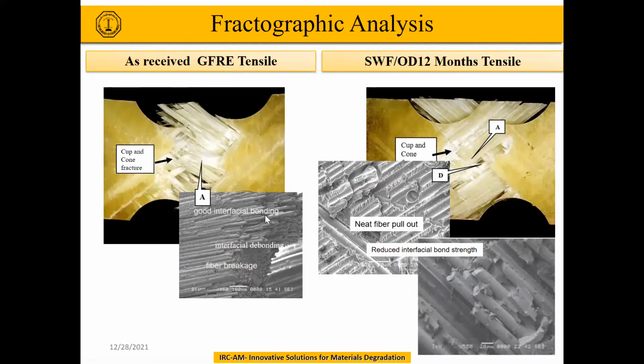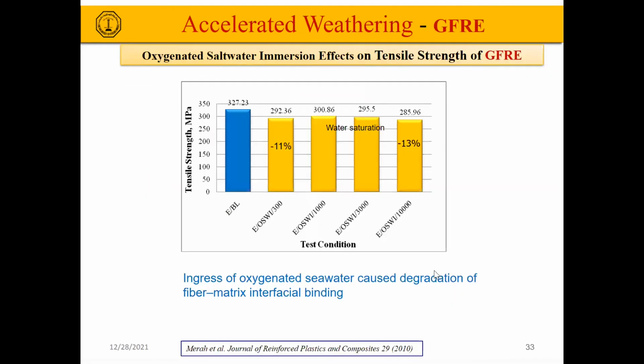We see that there is good interfacial bonding. There is interfacial debonding, and there is fiber breakage. But you can see that the fibers are well embedded into the epoxy. For 12 months exposure, you can see that there is a neat fiber pull out. There is a reduced interfacial bond strength for this area here. So there has been degradation of the interfacial strength between the fibers and the matrix.